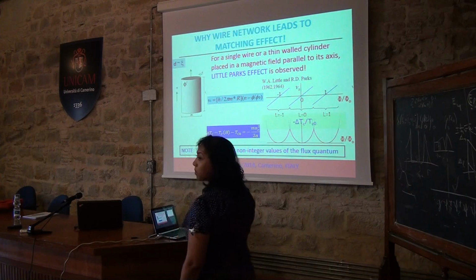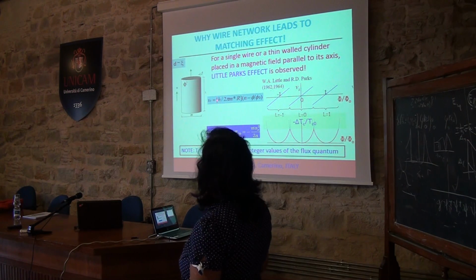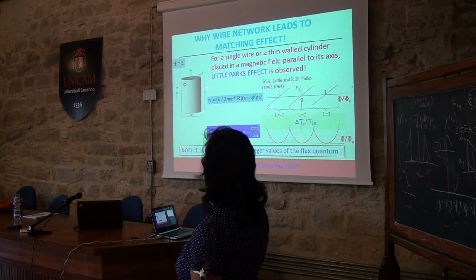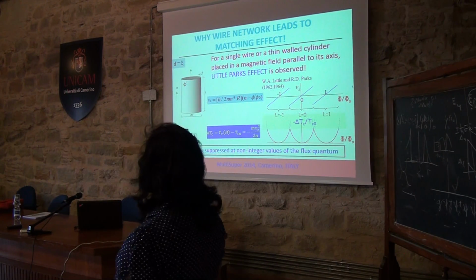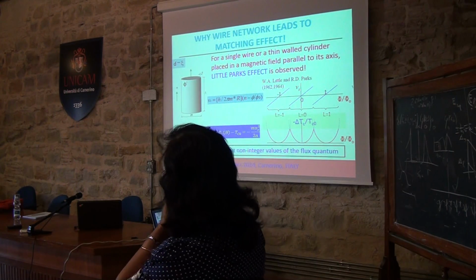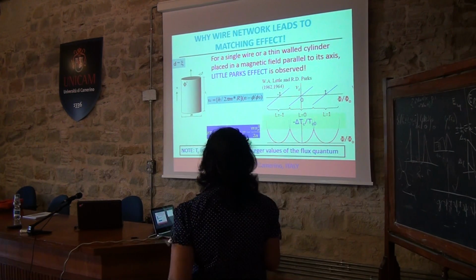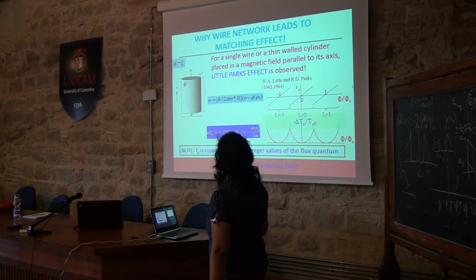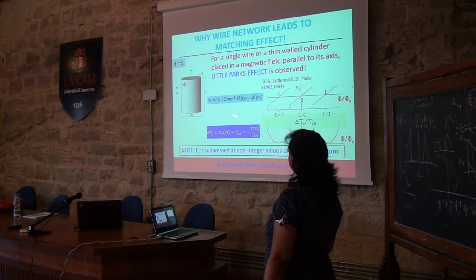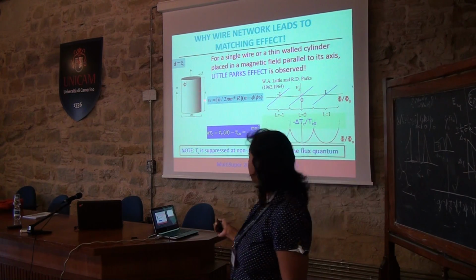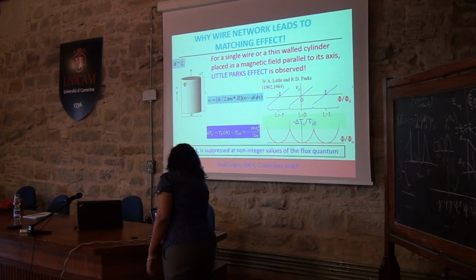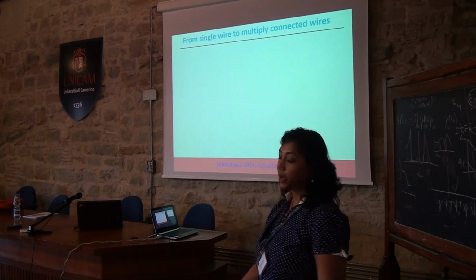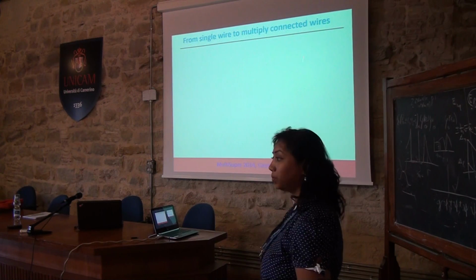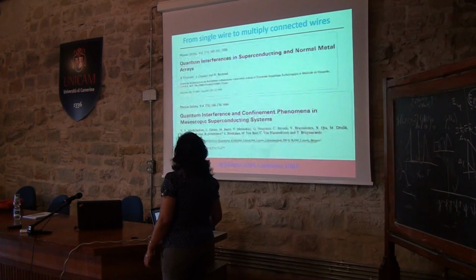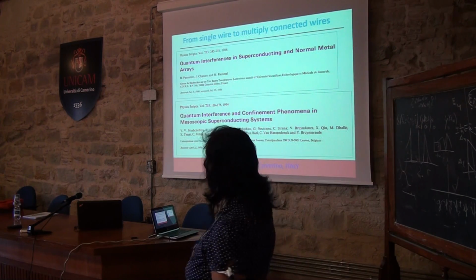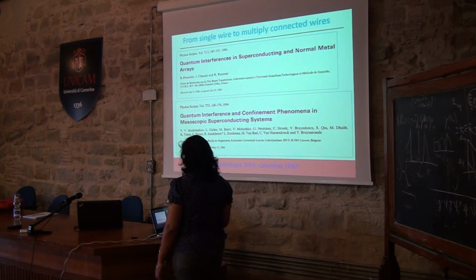Now, the explanation of this matching effect observed in these networks comes from the Little-Parks effect, which is evident in a single thin-walled superconducting cylinder, and it comes from the oscillation of the superconducting kinetic energy. This gives rise to these oscillations in Tc. However, the Little-Parks effect is seen in a single thin-walled superconductor. So people wanted to understand why such matching effects are also observed when you move to multiply connected wires. The answer was obtained from some theoretical calculations which incorporated quantum interference effects.